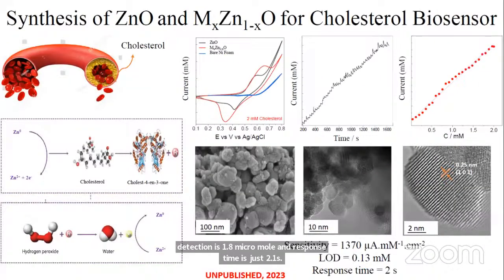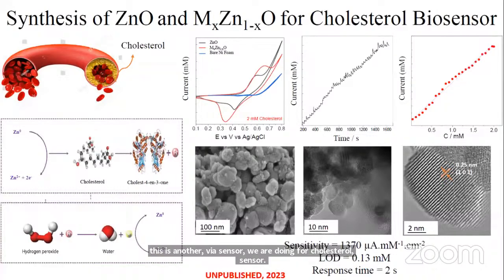And this is another biosensor we are doing, a cholesterol sensor, with a sensitivity of 1370 and LOD of 0.13 mM. Then response time is just 2 seconds.